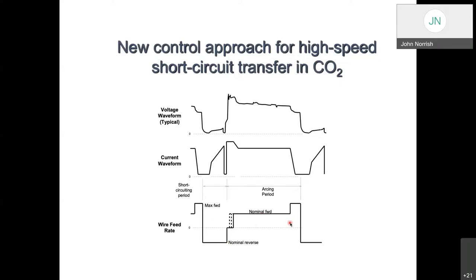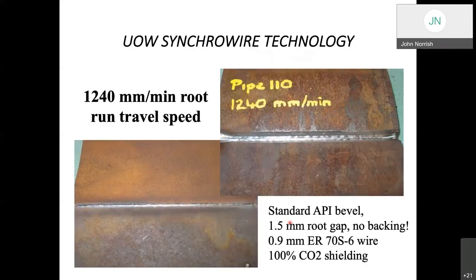The result of that was we could produce welds in a root run of a girth weld on a pipe at about 3 times the speed that you could do it with STT or conventional waveform controlled transfer. The other thing that was remarkable about that is that we could use 100% CO2 shielding with very smooth transfer and very little spatter.